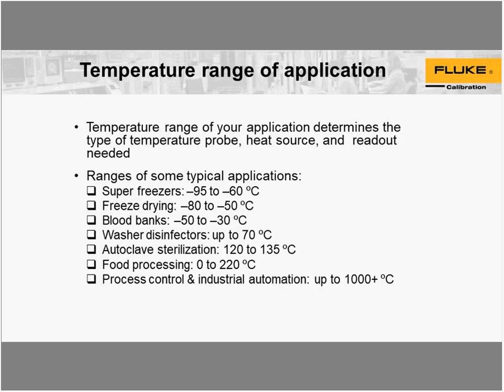All right, so we need to have a couple of things ahead of time. We need to know what the range of our application is, what temperature range we need to run our calibration through. Some typical ones out there have different ranges. Super freezers, cryo -95 to -60, freeze drying -80, blood banks from -50 up to -30 degrees, disinfectors around 70 degrees, autoclaves, food processing and process control instrumentation all above zero, and they can get quite high in temperature.